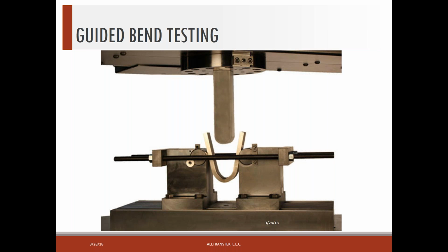And a point I should make about the plunger, which you can see, the rounded part that is pushing down on the bend specimen, that plunger has different diameters for different types of material. If we're welding some high strength material, or we're welding some aluminum, the higher strength aluminums, then typically the diameter of that plunger will increase, because if we try to bend it at too sharp of a radius, it will fracture just because of the material properties. So that plunger diameter is not always the same.